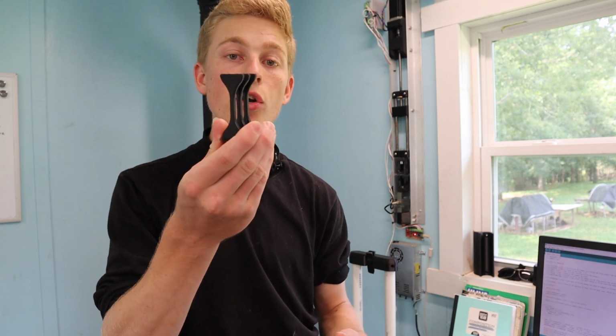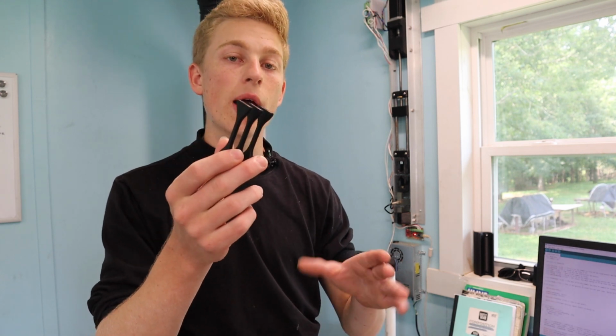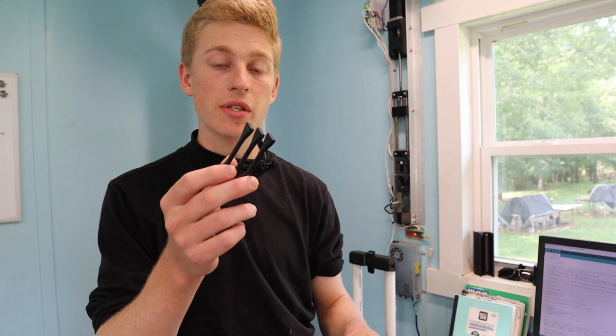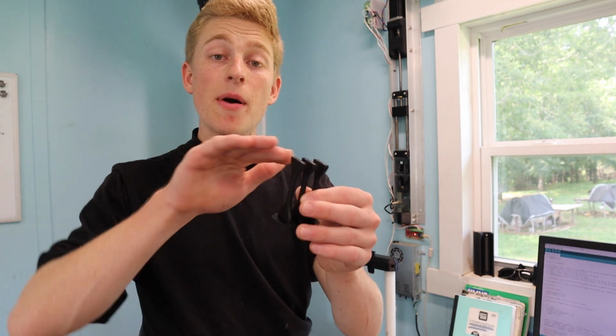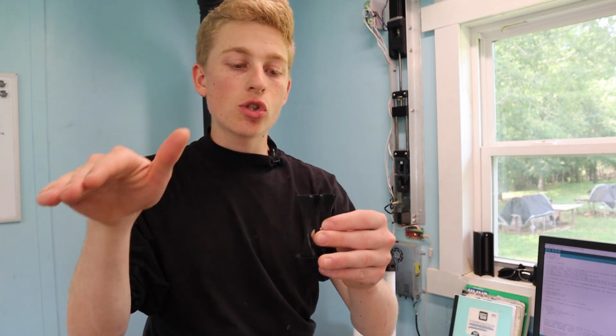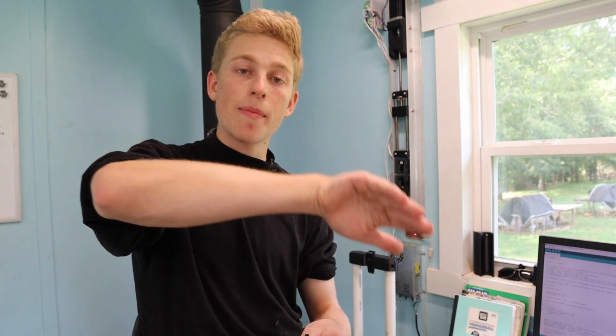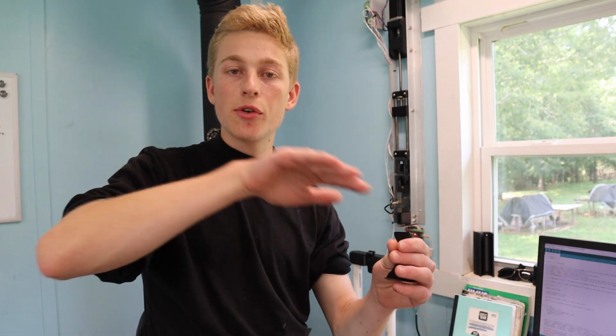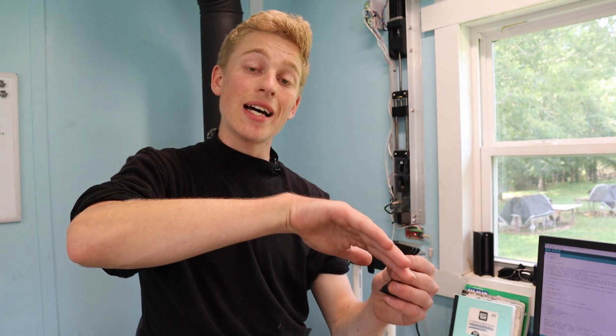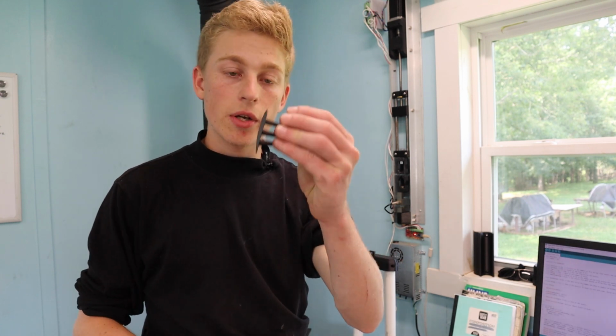With this plastic here, the optimal temperature was right about 250 degrees Celsius for the nozzle. Above that, it starts going back down, you start losing strength. Below that, it dramatically drops off. So I tested from 200 to 260, and you get a lot of gain in strength up until about 250, and then you drop off again afterwards, going back down the other side. I assume because the material is degrading because of the high temperature, for whatever reason. But I do that in order to find the optimal temperature for printing whatever material I'm testing.